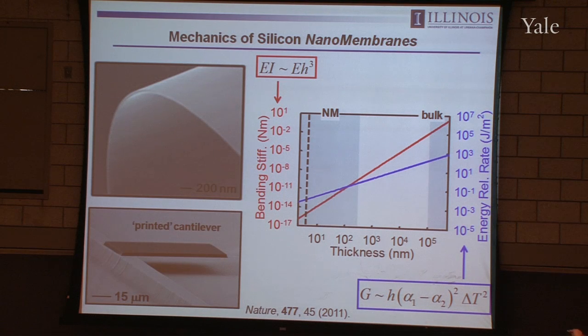And in fact, for thermally driven crack formation, where the change in temperature of the system is driving cracks, typically differences in coefficients of thermal expansion will cause interface cracks to form, but the energy release rate associated with opening of those cracks is decreasing linearly with thickness. So that means the energy release rate when you go from a wafer to a nanomembrane form of silicon decreases also by orders of magnitude. So ultra-thin silicon is floppy and it's sticky.